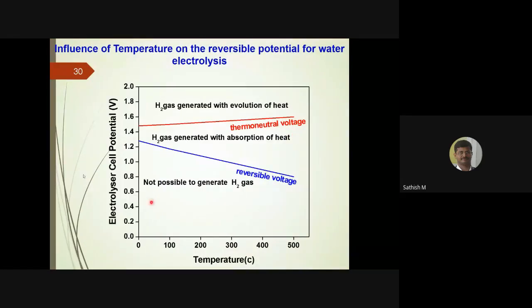This is another interesting slide where you could see that you not only produce hydrogen, you also produce some heat. This is the reversible voltage, and this is the thermoneutral voltage. Below this, you cannot produce hydrogen gas. Above this, you can produce hydrogen gas with the evolution of heat. In this area, hydrogen gas is generated with the absorption of heat. So people generally prefer this temperature and potential window to produce hydrogen by water splitting.